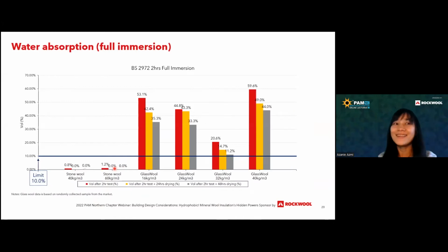Okay, that's partial, fully immersions. Similar to partial, I also looked into the differences of Glasswool and Stonewool. What are the values after the test? Similar, we did 2-hour full immersions, we tested straight away, and then we tested at 24 hours, and then at 48 hours. If you can see here, Stonewool is only around 0.8% as well as 1.2%.